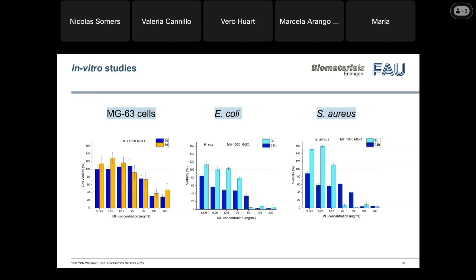So I don't show them here, but what I can say is that in general we didn't observe really an effect on cells, but we could really see an effect on the bacteria when both were combined. When we have the bioactive glasses alone, they had to a certain extent an antibacterial effect. But when we combine this with the honey, it was much higher than the honey alone or the glass alone. So this was quite